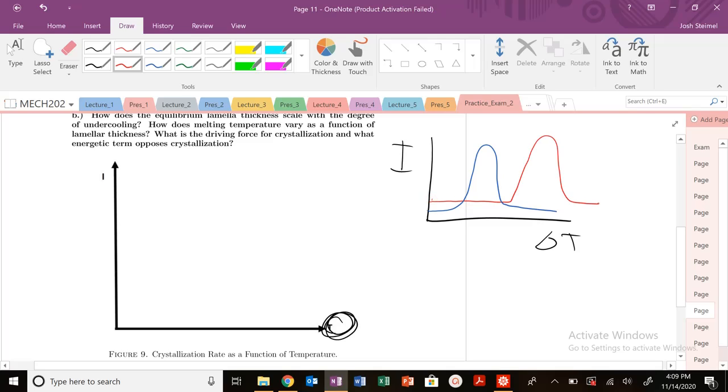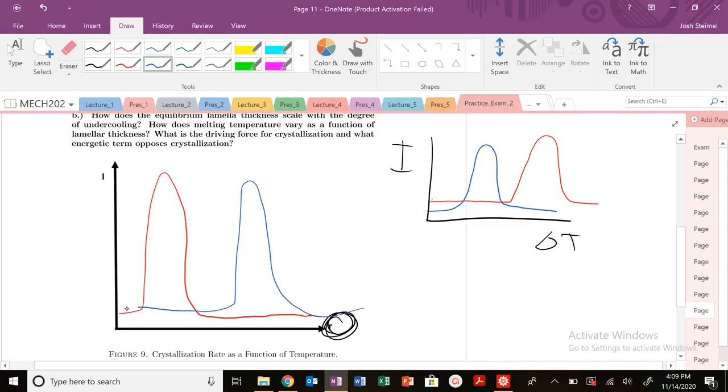I need more undercooling. So essentially, if this is temperature, and I need large undercooling, I need A to be at very low temperatures in order to crystallize, whereas for my blue, I could go just like this. It's useful to work in between these plots, but always check what this value is here. For blue, at high temperatures, what's dominating here? Diffusion or growth. What's dominating here? Nucleation. So at low temperatures, nucleation dominates. Again, it's just the flip, the reverse here.